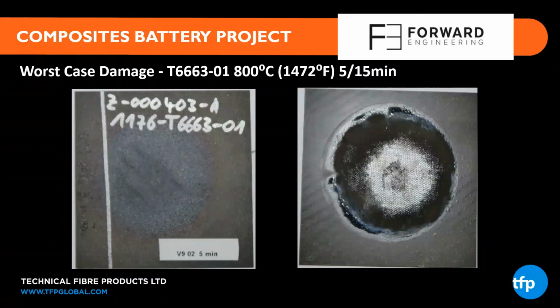These pictures show the worst case damage in the T666301 laminate from the 800 degrees centigrade experiments. On the right, you can see the exposed face of the laminate, and due to the high temperature and the ablative effect of the gas flame, some of the resin has been burnt off. However, the photo on the left shows the back face of the laminate, which has experienced significantly lower temperatures due to the insulating effect of the Technofire. And you can see there's no distortion, delamination, or degradation of the laminate structure, with just some minor discoloration. This highlights, in a thermal runaway event, how the intumescent mode of action of Technofire can protect the composite battery enclosure structure.